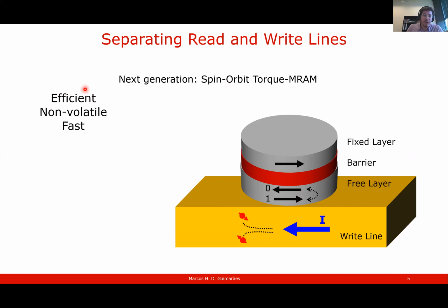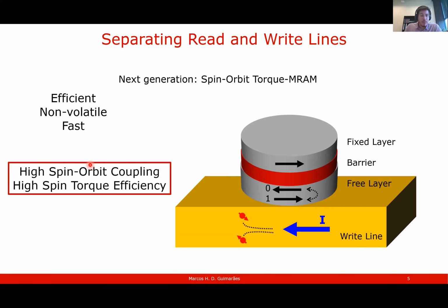There are several advantages of the spin orbit torque MRAM over the STT MRAM. It's efficient, it's non-volatile, because it's magnetic like the STT MRAM, but this is an advantage over the standard RAM memory that we use in our computers, and it's fast. So it can be used the same way that we use the SDRAM. And for increasing the efficiency here, this write line needs to be composed of materials which show high spin orbit coupling, and this converts into a high spin torque efficiency.